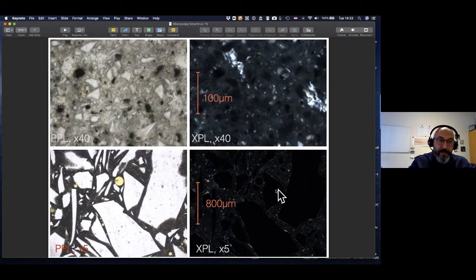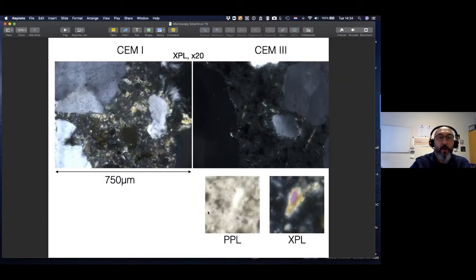On the bottom row, you're seeing glass aggregates. They are not slags. They're just aggregates, very large aggregate particles. But in cross-polarized light, again, you see quite dark, give or take similar features. Why? Because they are also amorphous. That's the reason they should show similar characteristics. But the only way I can tell that this is not a slag, but a glass particle, is to check my scale. So please, oh please, whenever you're dealing with photomicrographs or micrographs in general, always use scales.